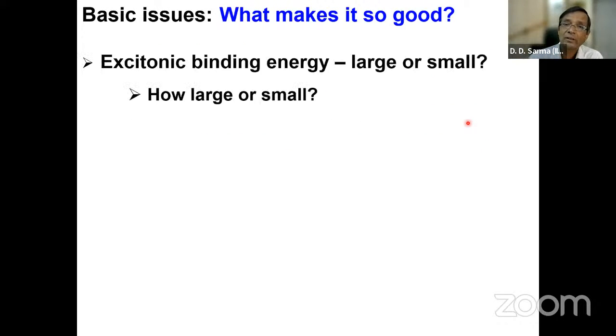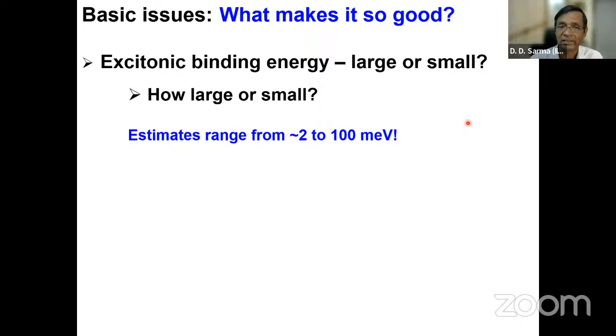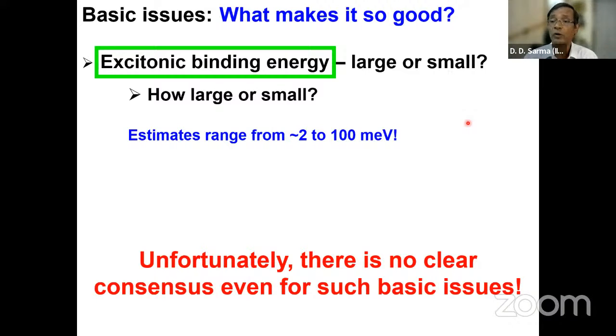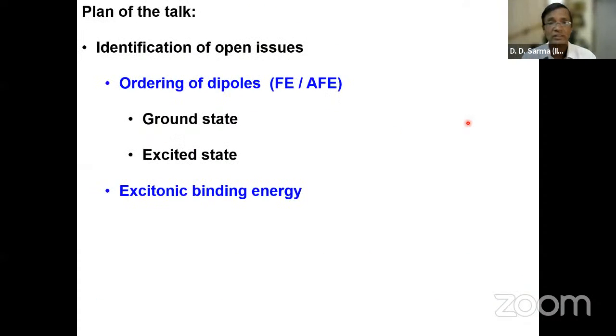And then the other question: once I create this electron and hole, they attract each other with a potential that we call the excitonic binding energy, the energy of binding of the electron and hole. I must overcome that to separate them. I would like this binding energy to be small, so that I can easily separate them. But if it is large, I won't be able to separate them. So we wanted to know what the excitonic binding energy is. It turns out that in the literature, the energy estimate was from 2 to 100 milli-electron volt, very widespread, which means there was no agreement on that, though it's so important a question. So there's no consensus when we went into this and started asking these questions.